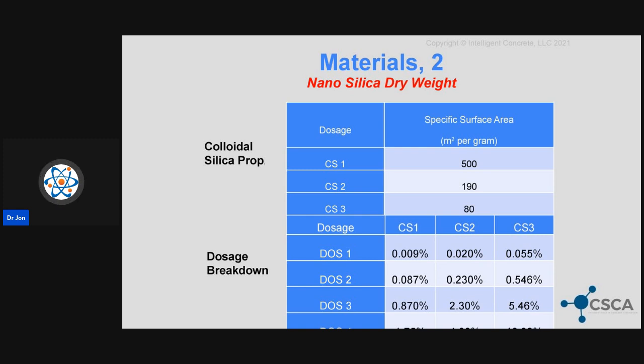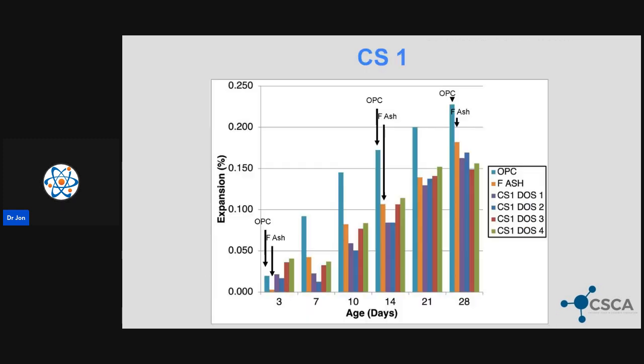So what we've got here is 3 discrete or narrow distributions, and I used them at 4 different dosages, where the first dosage represented an equivalent amount of silica that would be brought by 20% class F fly ash. Then we increased it by an order of magnitude, so to 200% fly ash, and then 2,000, and then 4,000% equivalent. We couldn't do a replica of that using class F fly ash in any of our mixes, so we stuck with that 20%, but we ultimately used colloidal silica that would have the same amount of specific surface area of reactive silica as the class F fly ash, and then, of course, those increased dosages.